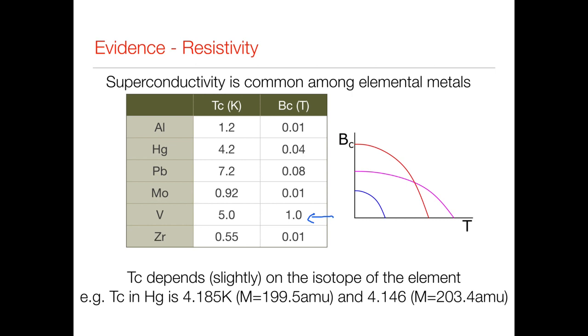Most of these critical fields are really quite small, so we're talking 1/100th of a Tesla. Vanadium, however, has a 1 Tesla critical field. That's starting to get to be sort of useful. So vanadium seems to be a little bit different from the other elements. For the moment, I'll park that thought, and we will come back to it in the final lecture as to why vanadium is different from the other materials. But at the moment, it's a little bit of an outlier.